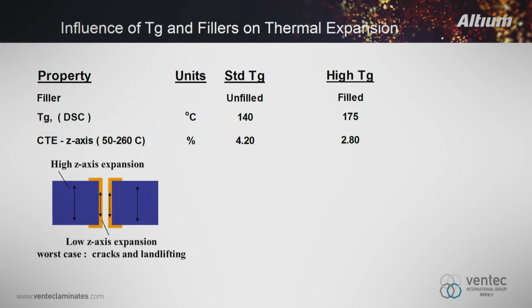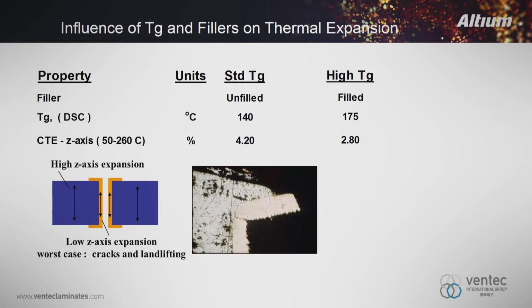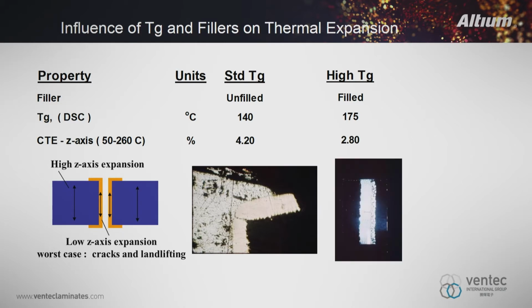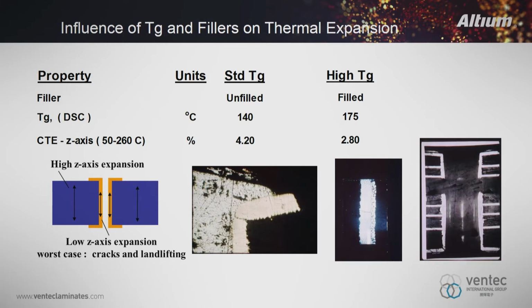And if you look at the pictures underneath, you can see the problem is you have a copper barrel. The copper is actually constraining the material. The laminate itself is expanding at quite a high rate. So you can get cracks. This is actually a crack on the corner of a hole, so the pad's lifted up and actually fractured at the side there. You can get fractures in the copper itself in the middle. You see a small crack in the center there. Or if things go really bad, we end up like this and the whole thing just falls apart and delaminates.